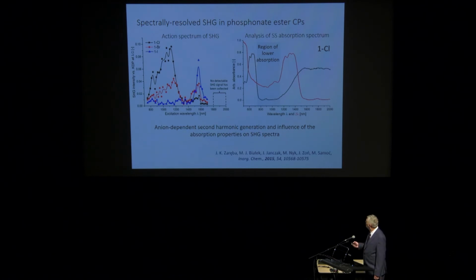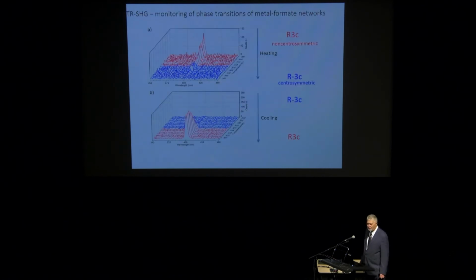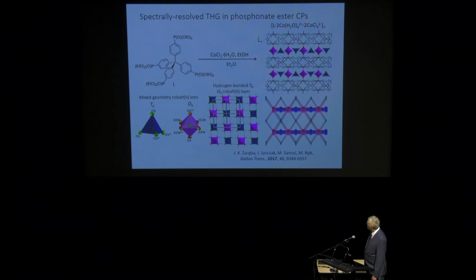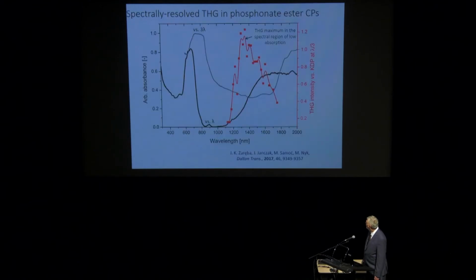Still, we're doing that. We're doing that, for example, for detecting ferroelectric transitions in which we lose the center of symmetry. We also use these powder measurements to detect third harmonic generation, which is again some sort of assessment of the suitability of a material for nonlinear optics. This is an example of such a measurement. Again, the spectral dependence of third harmonic generation is mostly controlled here by the presence of absorption.